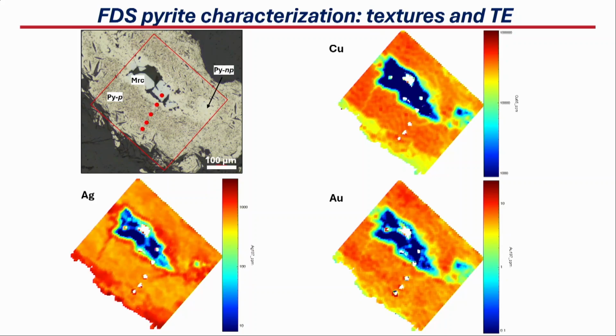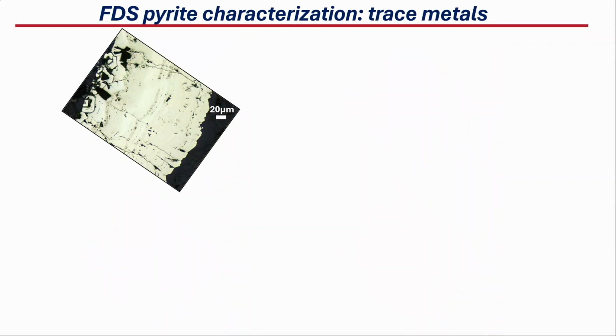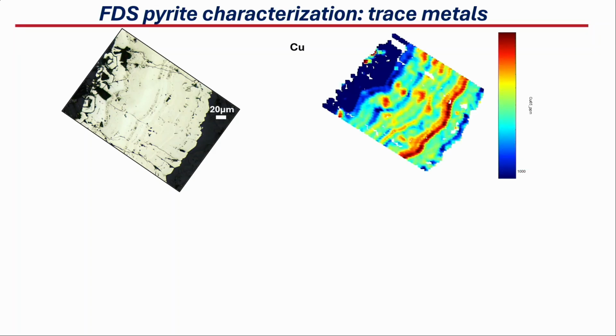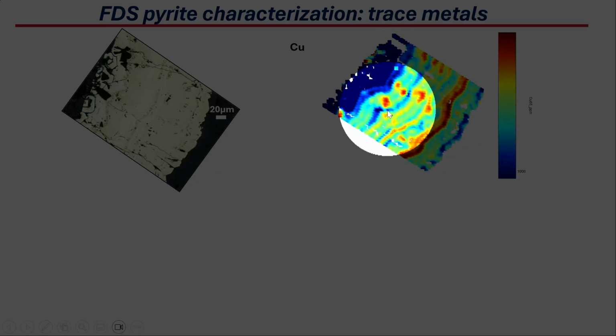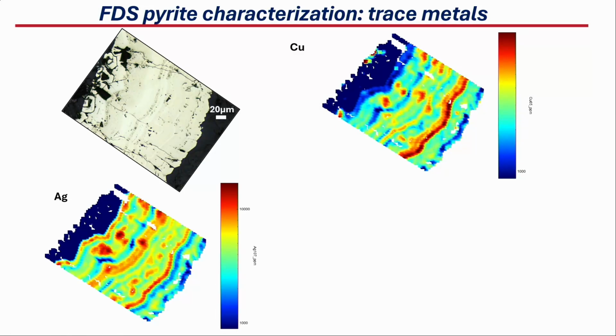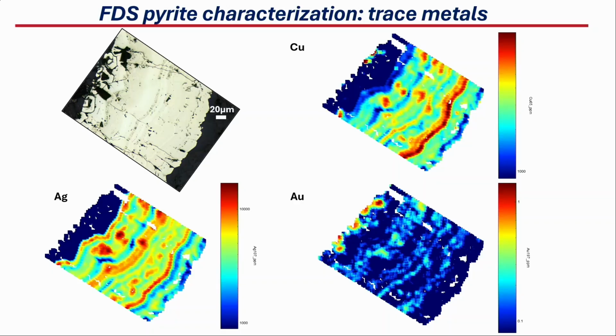Now if we analyze one of the other pyrite types, in this case the colloform one, let's see how the metals are distributed. We see that copper again shows an oscillatory zoning, but this region over here is pretty copper depleted, and that's correlative with the non-porous pyrite. Silver has a pretty similar distribution, although they are not completely correlative. But we see that this non-porous pyrite is depleted in silver, and then we can reach up to 2 weight percent of silver in colloform pyrite. And finally, gold, we actually have 1 ppm of gold in the non-porous pyrite, and nothing, or well, just some areas with less gold, but I would say it's gold depleted.